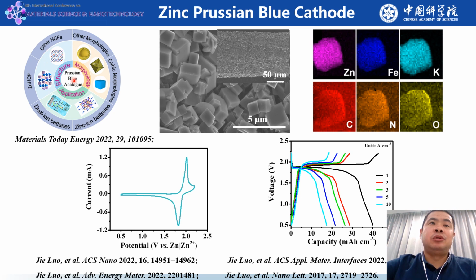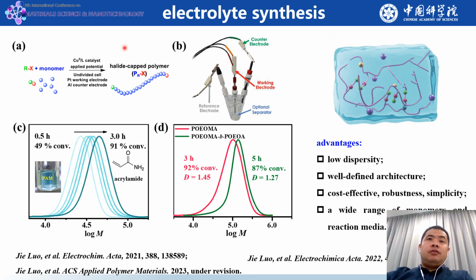The popular Prussian blue and its analogs received many concerns in the field of energy storage. Zinc Prussian blue is proposed and synthesized. As you can see, the beautiful cubic zinc Prussian blue is uniformly distributed on the carbon nanotube fiber, and which illustrates beautiful, highly reversible CV curves and a potential as high as 1.9 volts, which is very useful for improving the sensor sensitivity. For the battery device, another important part is the electrolyte.